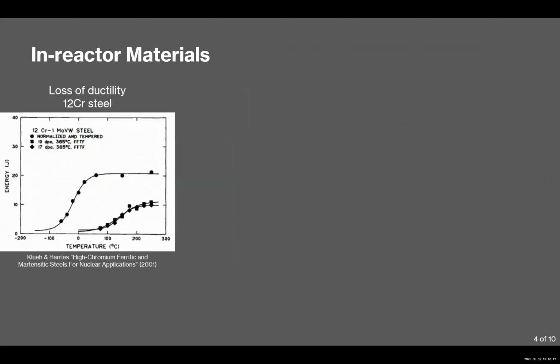So what does this actually do? Radiation damage, these are just some examples of how bad could it be. Why do we like metals in structural materials? Because they can flex a little bit and not break. But in radioactive environments, your metals can go from being very ductile. Here is a plot of energy to breakage against temperature. For a normal material, we can absorb a lot of energy at room temperature and not break. Whereas if you irradiate, this has just been taken into a fission reactor for some amount of time, you can start to have brittle fracture rather than ductile fracture. When something starts to break, you want it to bend a little bit, you don't want it to just snap. So big degradation there.